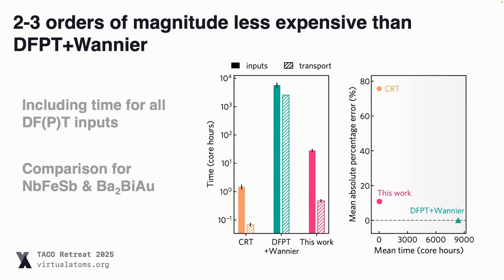And just in terms of the timings, here we've got the time taken to do different parts of the calculation. So the solid bars, those are the inputs, the DFT calculations, and the hatched bars, that's the actual transport calculation. And you can see that this is a log scale as well. So constant relaxation time is very cheap for both parts. In our work, most of the computational expense is calculating the first principles inputs. Actually obtaining the transport properties is very, very quick.